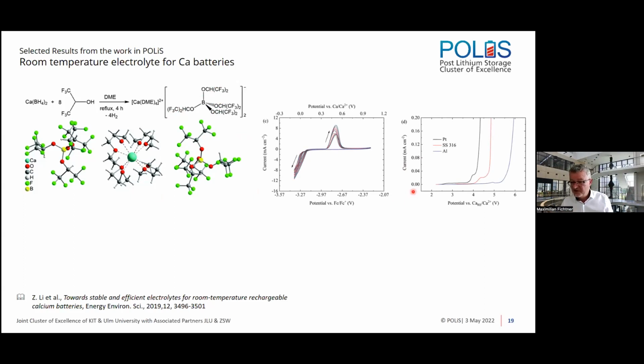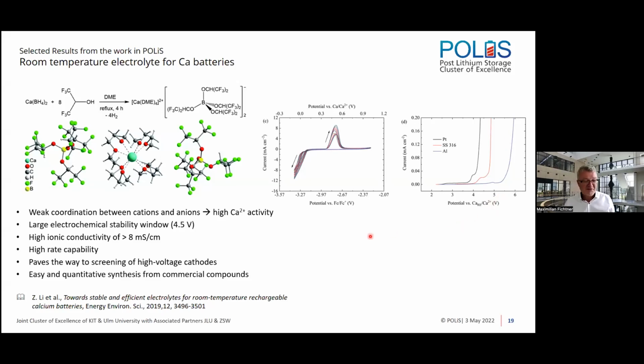And the properties are quite amazing, I have to say. It strips and plates very well here. The stability is very good. It's around 4 volts or higher, depending on how you make it. It's 4.5 volt here. The ionic conductivity is comparable to that of lithium electrolytes. We have measured 8 to 11 millisiemens per centimeter. So you get a high rate capability, and this allows you also to work with high voltage cathodes in case you have one. And as already mentioned, this is a quite easy and quantitative synthesis from commercial compounds.